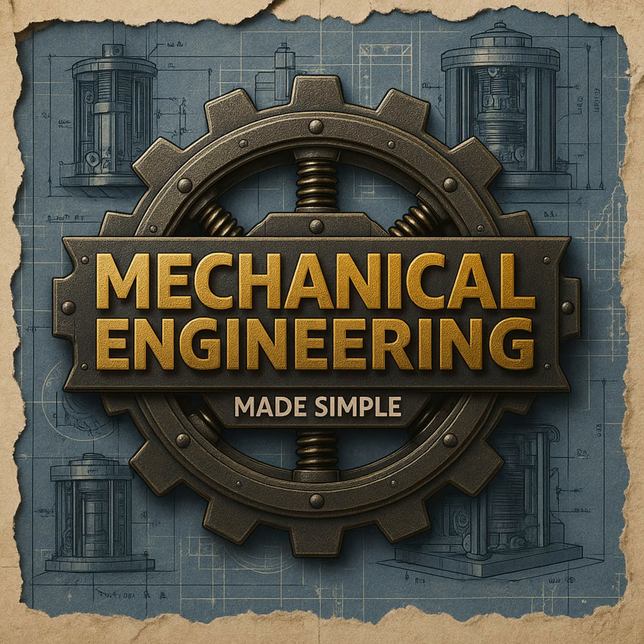That's terrifying. But what if I'm on the other end of the spectrum? What if I'm not designing a thin aerospace soda can, but a massive, thick-walled hydraulic pipe for an excavator? In that heavy machinery regime, your wall thickness is very large relative to your cylinder radius. If you plug those chunky numbers into the formula, epsilon plummets to a very small decimal, like 0.5 or less. And when epsilon is tiny? The curvature effectively ceases to matter. Really? The thick walls possess so much inherent bending stiffness that the hole cannot physically bulge outward. The structural integrity holds the curve, and the thick pipe behaves almost identically to the theoretical flat plate we started with. It's fascinating. Epsilon is a beautiful metric because it mathematically guides your physical intuition, telling you exactly when curvature is a deadly threat and when it's negligible.